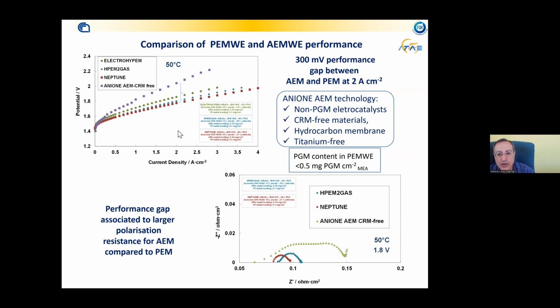So there is still a long way to go to bring the performance of AEM technology close to PEM technology. But using AEM, we don't have any critical raw materials, we don't have precious metal electrocatalysts, we have hydrocarbon membranes instead of perfluorinated membranes, and we use steel, stainless steel, instead of titanium. So we have significant advantages, but still an efficiency gap.